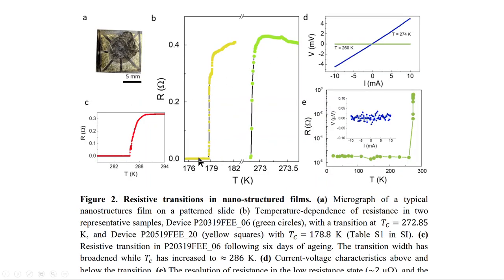And they still report these resistive transitions. So here you see at the higher temperature, 274 Kelvin, you see this IV curve here, and then at 260 Kelvin, you see that it's basically flat, so there is no voltage. And so this is what you would expect if you had a vanishingly small resistance.